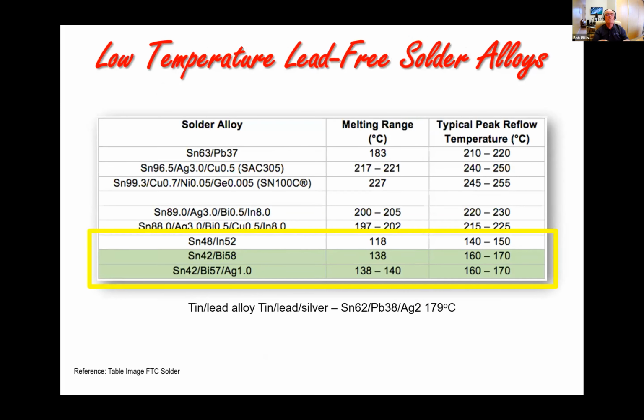And basically, there are a couple of different families. First of all, the tin indium material, which has been around quite a long time. And I've used this for rework of BGA packages successfully. However, the disadvantage of that is the cost of the raw material, the total raw material. We've got tin bismuth and we've got tin bismuth silver. Again, these materials have been around for quite a few years. They weren't really considered too much during the implementation in the US and Europe during lead-free, because the materials have been proved and been demonstrated to be more brittle than existing materials within the industry. That's one area we need to consider and think about.